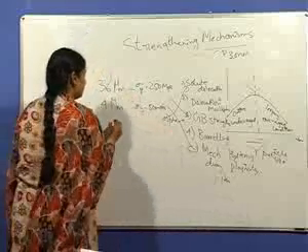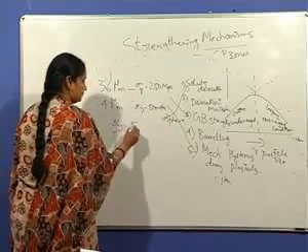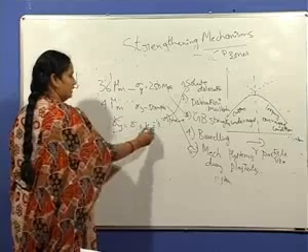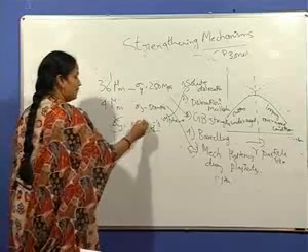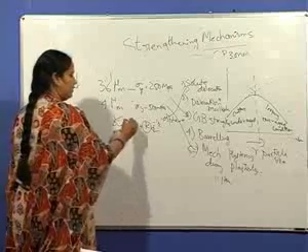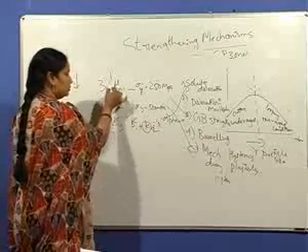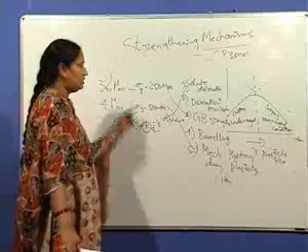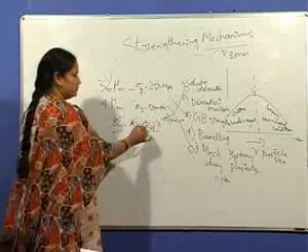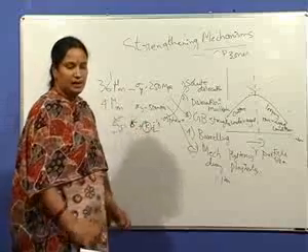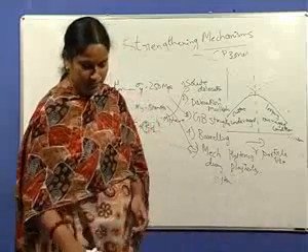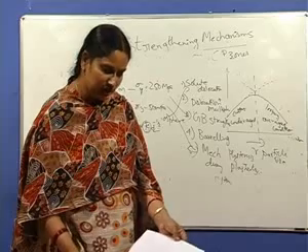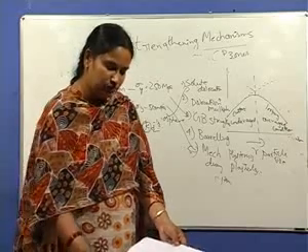The formula for this is yield stress is equal to friction stress plus K d to the power of minus half. Yield stress is given, grain diameter is given, K is the locking parameter, the constant for a material. You have to find out sigma i. You have 2 equations, substitute to find K and then find out sigma i. The answer comes to be 250 MPa. So these are the questions in the previous papers from 2007 to 11 that I have found.